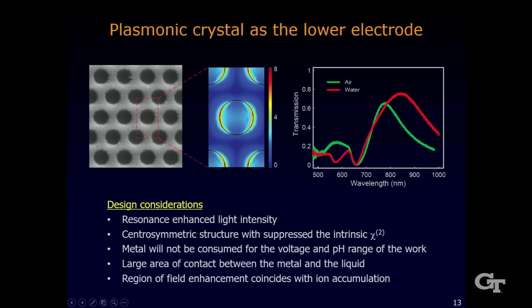It looks simple, but when you design the experiment, there are a few very important considerations. So this structure is designed to have resonance enhanced light intensity at the wavelength of interest, in our case, around 850 nanometer in liquid solution. And the structure itself is centrosymmetric. That means the background Chi2 response can be effectively suppressed. And more importantly, we need to make sure that the metal, even for gold, is not consumed for the pH value and the voltage that you use in the experiment.